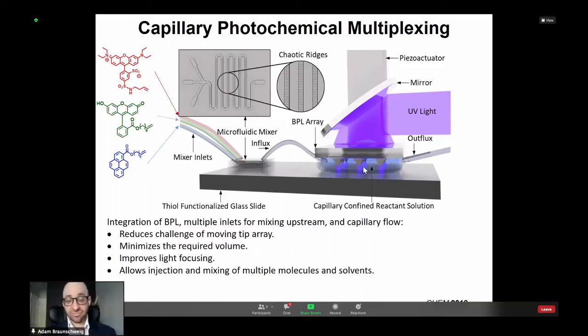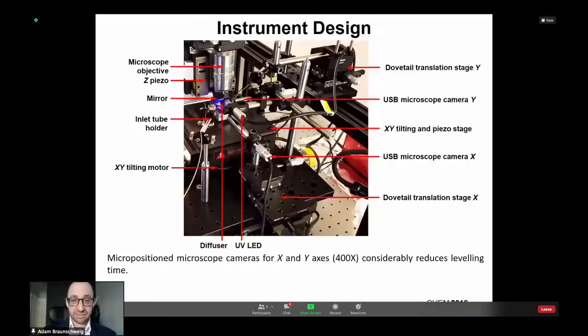So what this involved was we built new microfluidics to change the inks underneath these pens, and here what we have are what are called beam pen tips. So what we do is we take the tips, we coat them in gold, and then we shine light through them so that we can ideally do either photochemical or mechanochemical reactions under the surface.